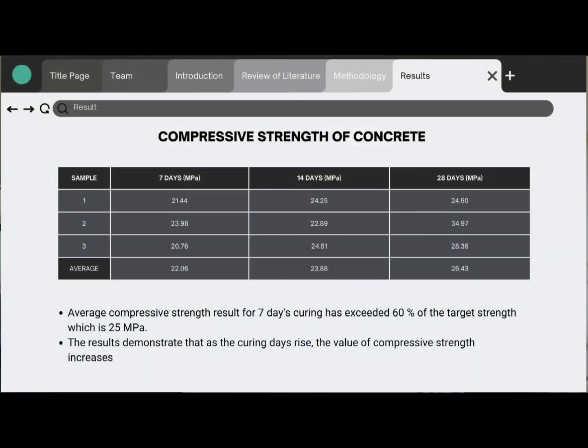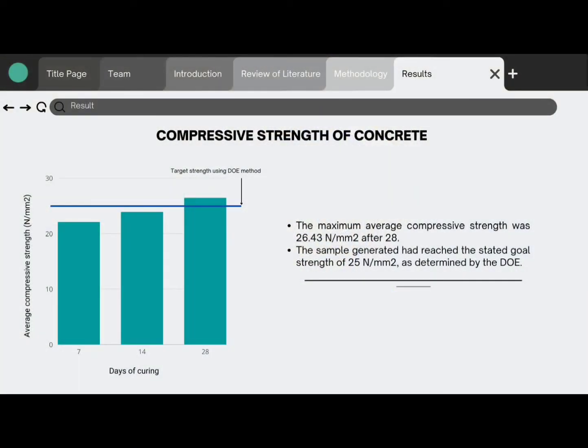So now I will go over the compressive strength of the concrete that we tested using the compression test machine. The average compressive strength result for 7 days curing has exceeded 60% of the target strength, which is 25 MPa, and as shown, the results demonstrate that as the curing days rise, the value of compressive strength increases. The maximum average compressive strength was 26.43 N/mm² after 28 days, which is already past the target strength of 25 N/mm² as determined by the DOE method.